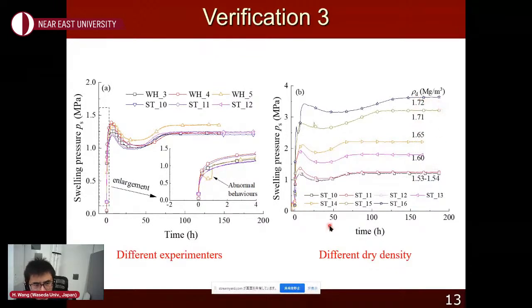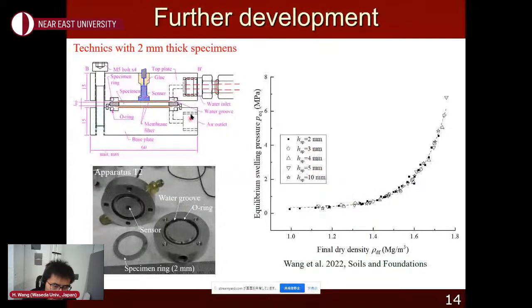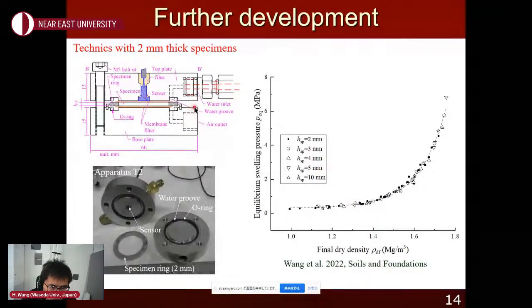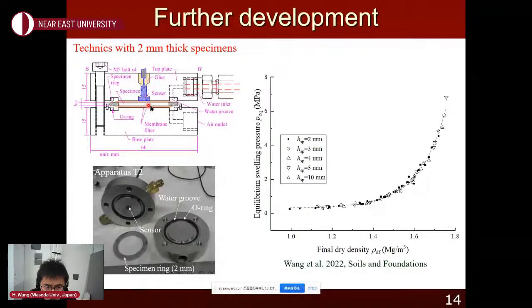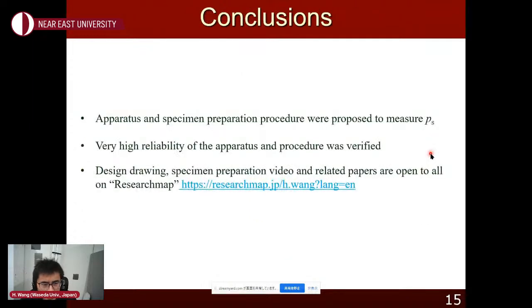Based on this technology, we also recently developed an even smaller sized apparatus. So the specimen thickness was reduced to 2 millimeters. Even with 2 millimeters, as you can see, the relationship of dry density and pressure is very unique. I mean, the scatter is very small compared to the past study.